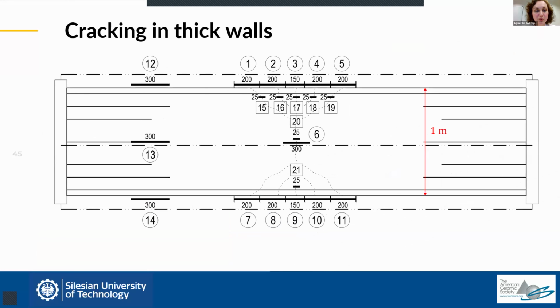The aim of this research is to investigate the development of cracks, and we have actually experienced the cracking pattern that I explained to you, but some other interesting observation has been made during this research: the height of the effective tensile area was not complying with what is assumed in Eurocode and many other standards around the world. Currently the state of the art says that the height of the effective tensile area in a tensioned element equals more or less 2.5 AS, where AS is the distance from the center of gravity of reinforcement to the free surface.